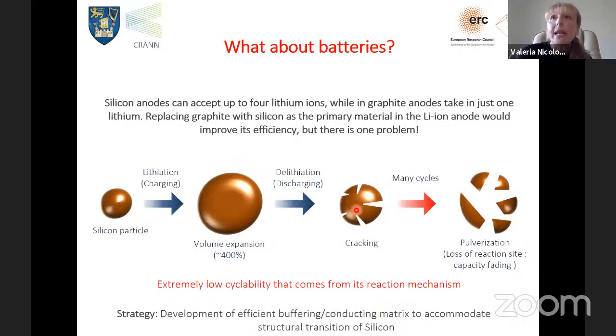But also, we needed a very good material for batteries, and indeed, silicon has been one of the materials that has been suggested as an anode for batteries for decades. But the community kind of dropped it aside, because it was not lasting very long. Silicon has a very high theoretical capacity. However, when you charge silicon particles, they expand their volume by about 400%. And when you discharge it, they start cracking, because their volume goes back to this 400 times less. And then eventually, if you do it for many cycles, you actually get pulverization of the anodic material.